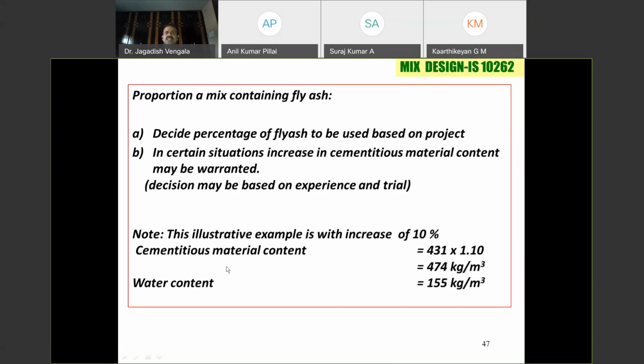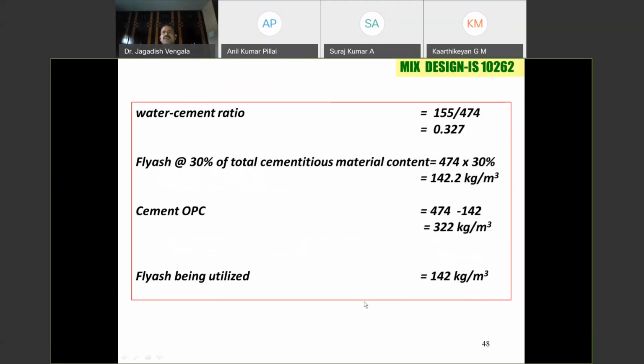But anyway, for high strength concrete, the limits are given now in IS 10262:2019. I will show you what the limits are. So it's a simple example. Suppose a 10% increase you have to do. Already 431 is your cementitious material, with the 10% increase it is 474. Then what is the water content? 155 kg per cubic meter. So how much is your water cement ratio? 0.327. Okay.